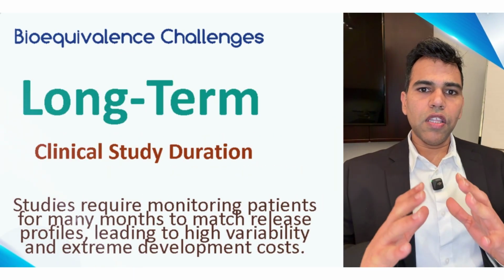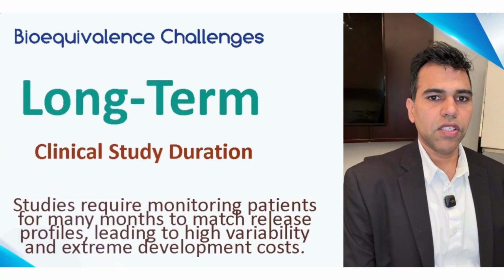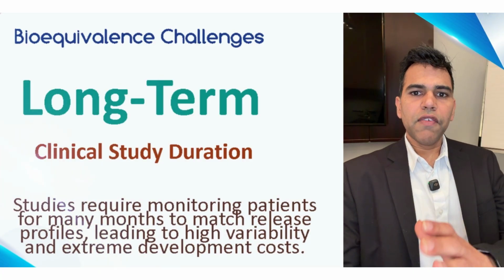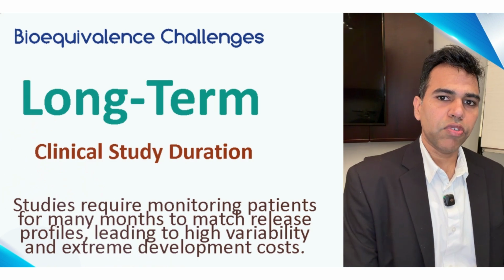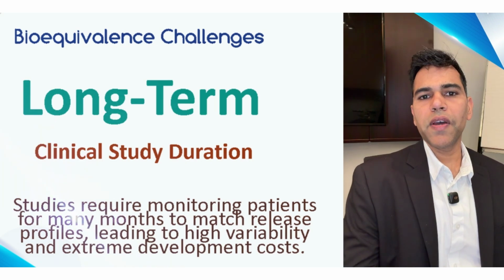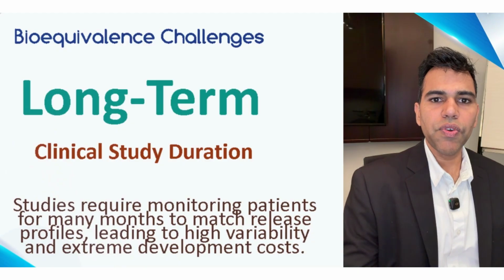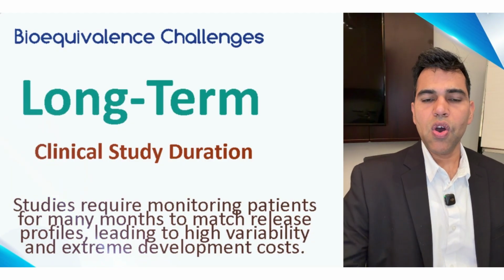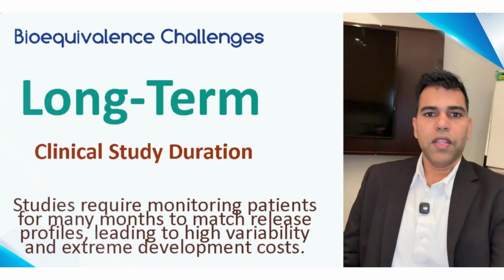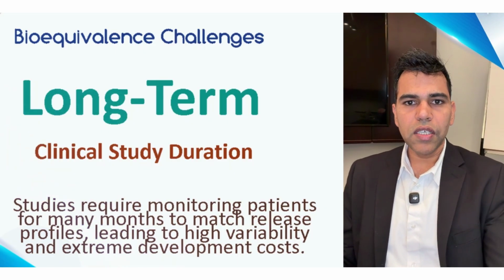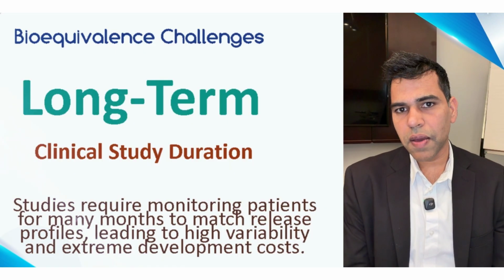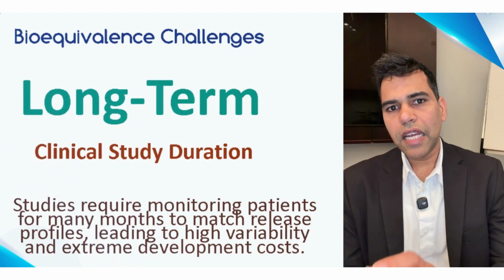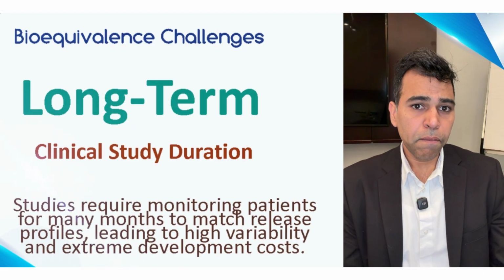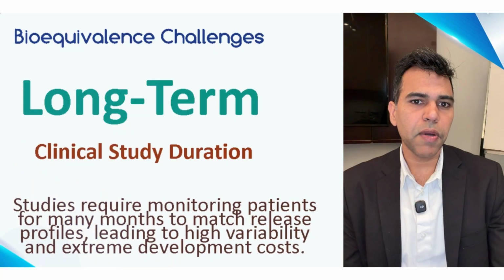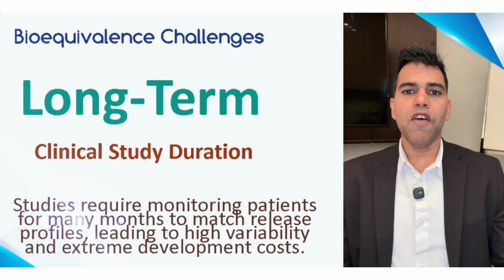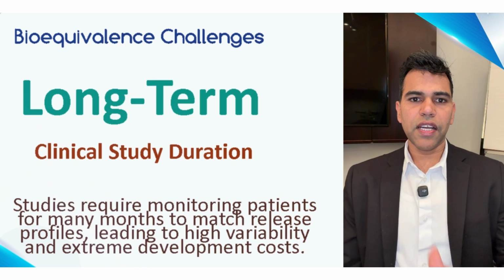Let me put the bioequivalence challenge in concrete terms. If you are developing a generic for a leuprolide depot 3-month formulation, your bioequivalence study needs to demonstrate equivalent testosterone suppression over a 12-week window. That means dosing patients, collecting blood samples over 3 months, and doing pharmacokinetic modeling. But drug release from a PLGA microsphere is not linear. You have the burst, the plateau, the degradation phase.